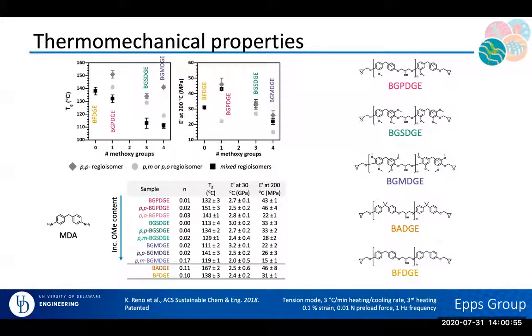Now we can take these materials. I won't focus too much on all the details of this slide, but I want to point out the two commercial materials: BADGE, the BPA-derived version, and BFDGE, which is the analog to BPA that does not have the two methyl groups on the bridge. If we compare those materials to our bio-based analogs, we can see similar glass transition temperatures, similar moduli at 30 degrees C of about 2 to 3 gigapascals, and similar moduli at elevated temperatures, at 200 degrees C, of about 40 or so megapascals.